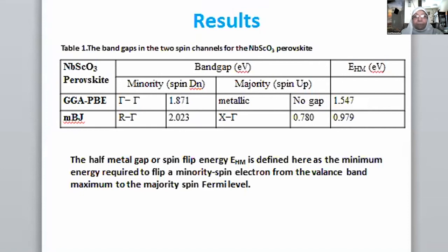Also in this, on the last column, I have put the half metal gap, not the band gap, but the half metal gap, which is actually the spin flip energy, which you can see in the case of GGA is 1.554 or 55, you can say, electron volts, which is the energy required for electrons to do a spin flip from the minimum. That's the minimum energy required, of course. So for the minority spin electron to go from the valence band maximum to the Fermi level of the majority spin. So this is the energy that we call the half metal gap energy.